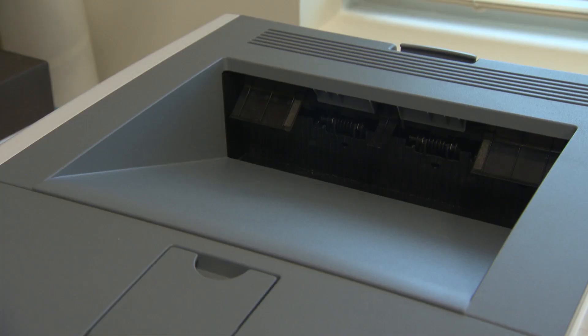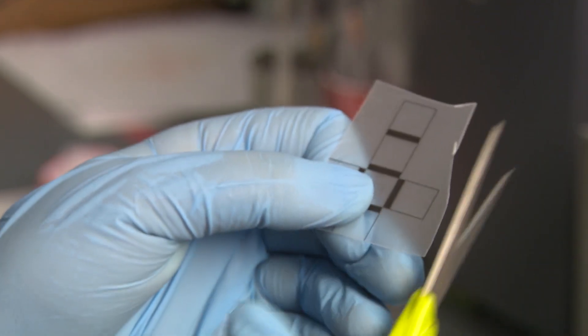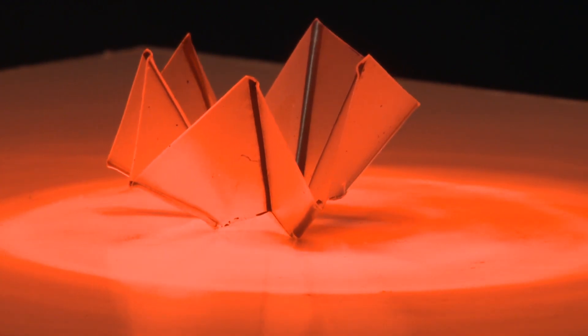It's a $5 light bulb that you can buy from Home Depot, so there's nothing special about it. Using a standard inkjet printer, black line patterns are printed on special plastic or polymer sheet, then cut out and placed under the infrared light. The black lines absorb light more effectively than the rest of the sheet, and that causes the regions patterned with black ink to get hot and therefore shrink, causing it to fold very much like a hinge.